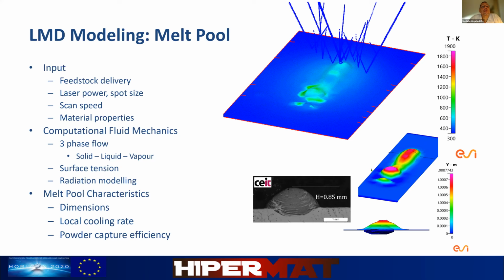The liquid state has a lot of complications in the sense you have surface tension, and because of the dependency of the surface tension on temperature, you will have things like Marangoni flow playing a major role on how the deposition at the end looks like. And if the energy delivered is too high, so if you have a high power, you might even evaporate the metal. That has several implications on how the melt pool will look like. Evaporation plays a smaller role in LMD, but it still takes place and it is accounted for.